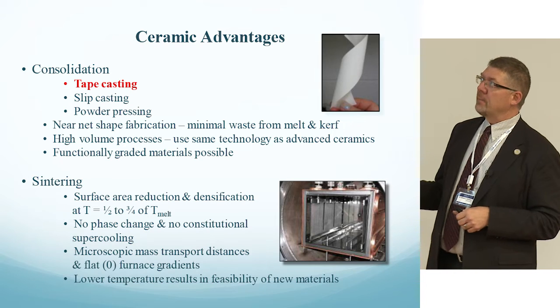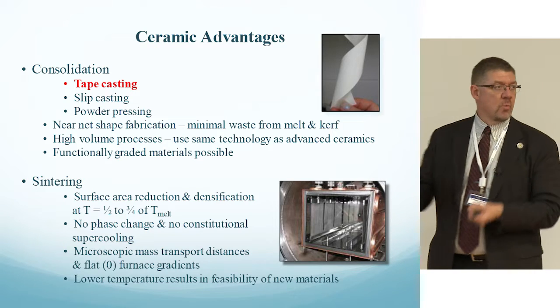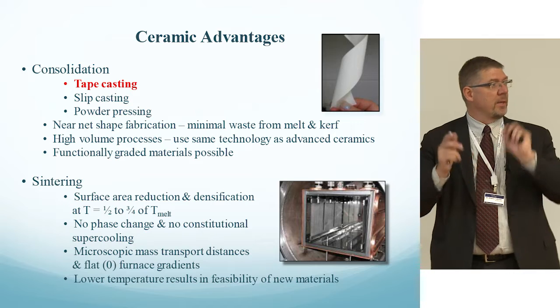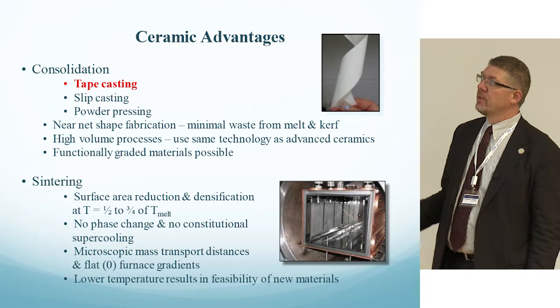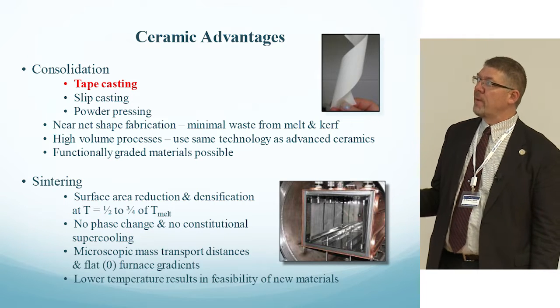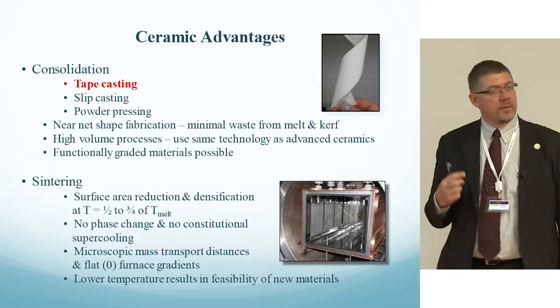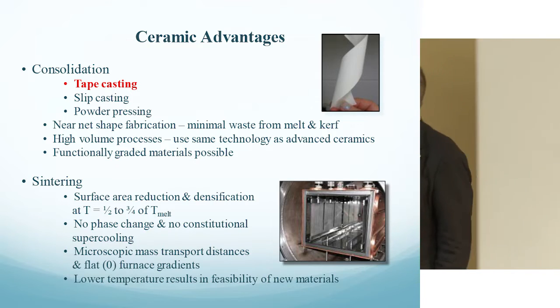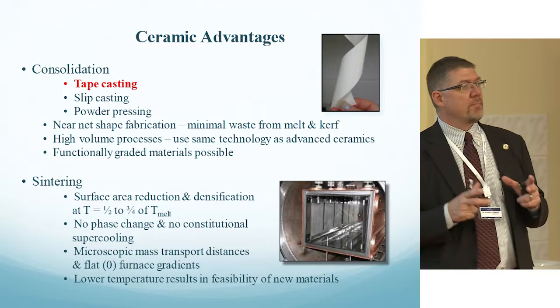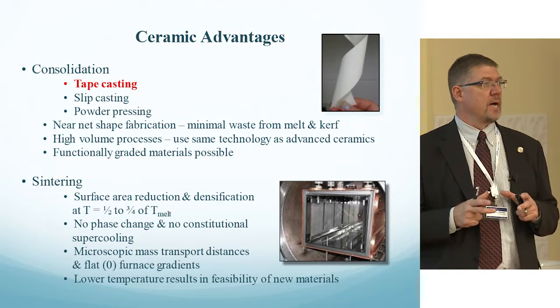You can do tape casting, which I'll get to later. This is just wet ceramic that you can take and twist and bend before it's been sintered. You can slip cast, you can press the powders into near net shape. And that's really probably the greatest beauty of this: if you're making a geometry that's extremely complex, like a